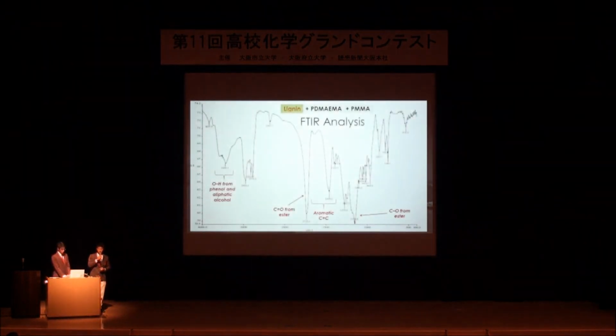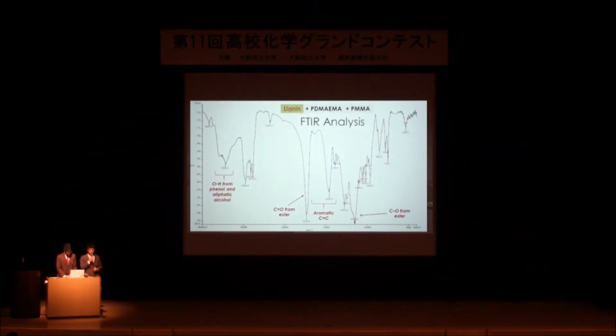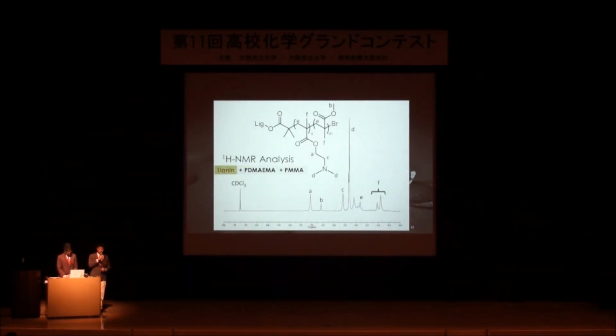This is the FTIR spectrum of lignin PDMA-EMA, PMMA. So in this spectrum, we can see the C=O double bond, as well as the C-O single bond stretch due to the ester group of DMA-EMA, as well as MMA subunits in the polymer. This is the proton NMR spectrum of our polymer. The peaks are assigned as shown. So from the NMR spectrum, we can also determine the ratio of DMA-EMA to MMA by comparing peaks A and peaks B.